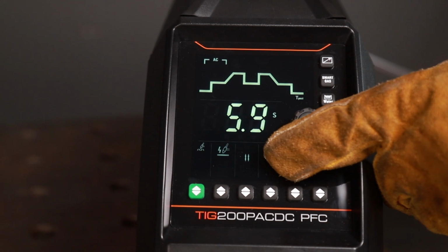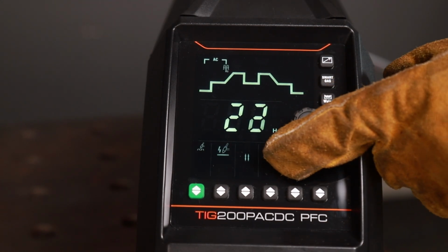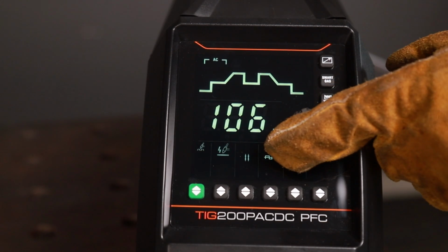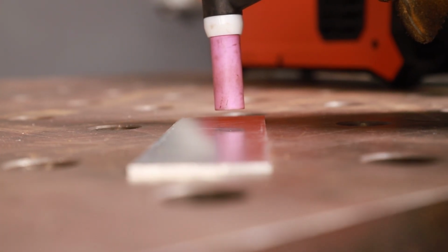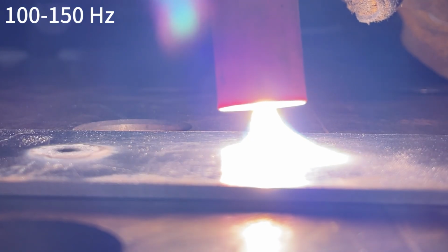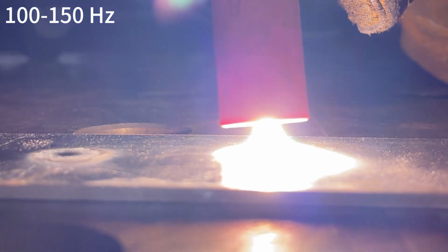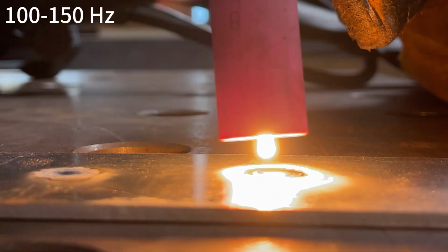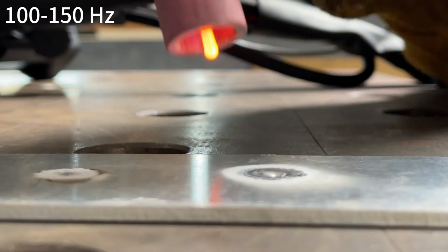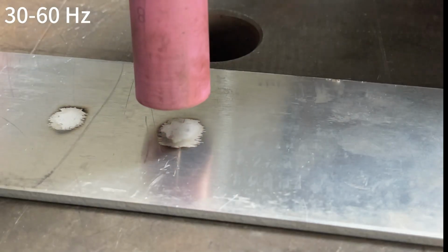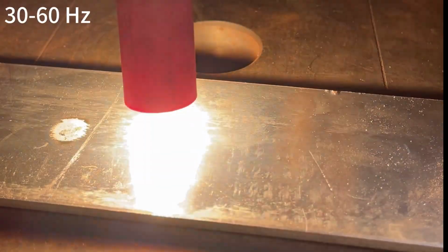into the metal. Additionally, AC balance control lets you adjust the ratio of cleaning to penetration, and adjustable AC frequency offers precise arc control. Higher frequencies narrow and stabilize the arc, allowing for more focused heat input and better control when welding thin materials or intricate parts. Lower frequencies widen the arc for increased cleaning action on thicker sections.